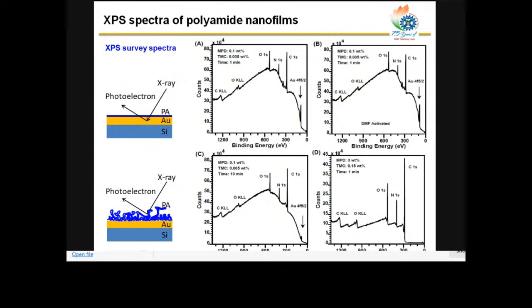Then we measured the chemical property of the polyamide nanofilm. From the XPS, X-ray photoelectron spectroscopy, you can see the constituent elements are carbon, nitrogen, and oxygen. For a very thin film, you can see the gold peak here, Au 4f5/2. And in the lower part, you can see that the film is crumpled. So I'm comparing here the smooth versus crumpled.